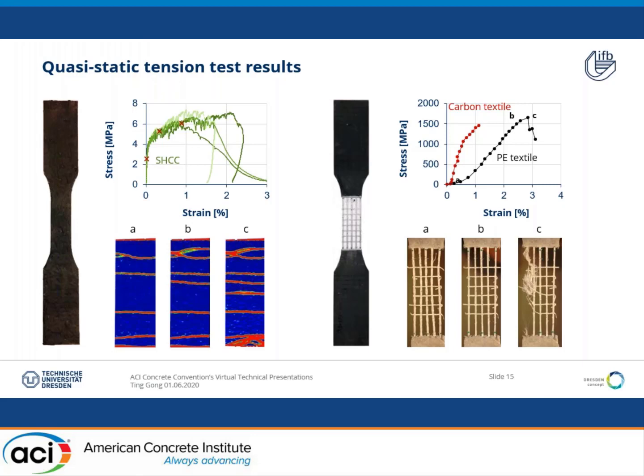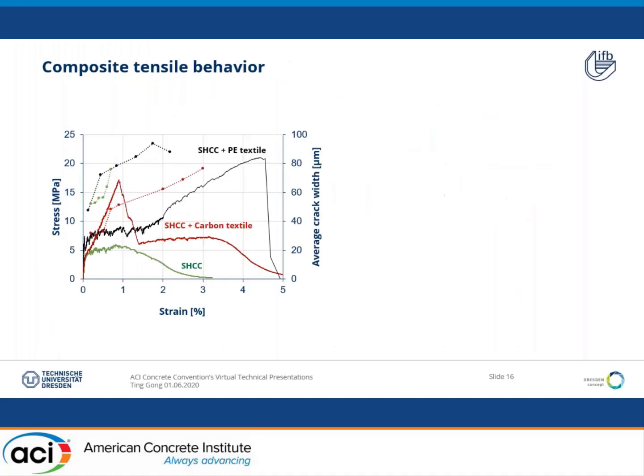This emphasizes the necessity of using continuous reinforcement in larger scale specimens in order to prevent premature structural failure. And if we compare the two types of hybrid-reinforced composites, we can notice that the average crack width in the case of carbon textile reinforcement is much lower, showing much better crack control, which corresponds very well to the single yarn pullout test. When the more ductile PE textile undergoes a larger deformation, there is considerable work to fracture energy. However, it should be noticed that this high level of work to fracture energy can only be achieved at a rather large deformation. In a scenario of a structure subjected to impact loading, the PE textile could not ensure sufficient confinement of the structural element due to the severe crack localization before the textile failure.